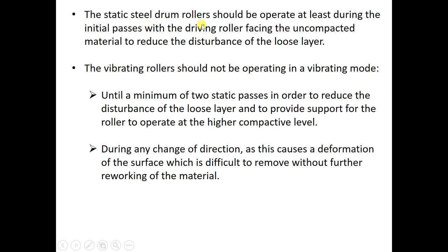The static steel drum roller should be operated, at least during the initial passes, with the driving roller facing the uncompacted material to reduce the disturbance of the loose layer. The vibratory roller should not be operating in vibrating mode in the initial stages. Do a minimum of 2 static passes in order to reduce the disturbance. Also, when you change direction, you need to turn off the vibratory mode.